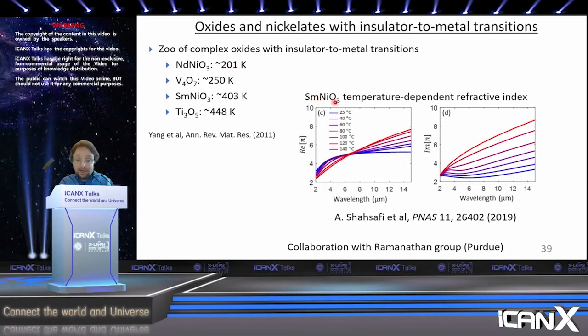And here's an example of another one of these materials. This is samarium nickel oxide, or samarium nickelate, and here's the real and imaginary part of the refractive index as a function of temperature, which we measured again with a spectroscopic ellipsometer. You can see this very large change in optical properties, which is quite exciting for tunable optics. But unlike VO2, there is no zero loss or low loss state. And therefore, this is very useful for thermal emission engineering, maybe less useful for some conventional transmission type optics. But you have to understand your material before you try to use it for devices.